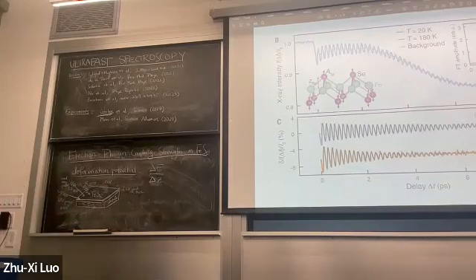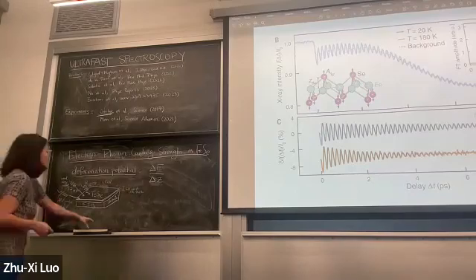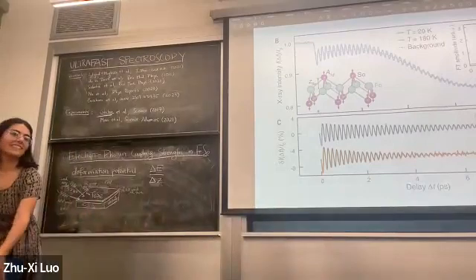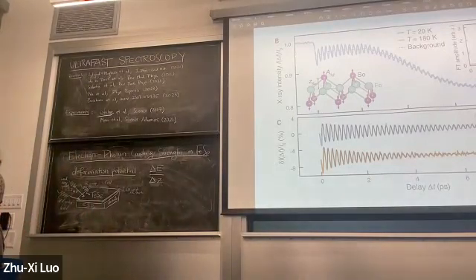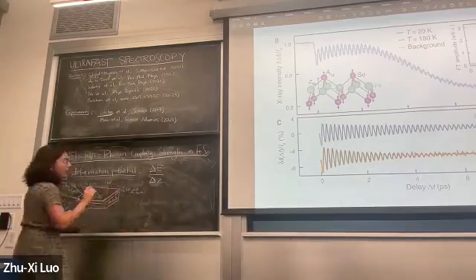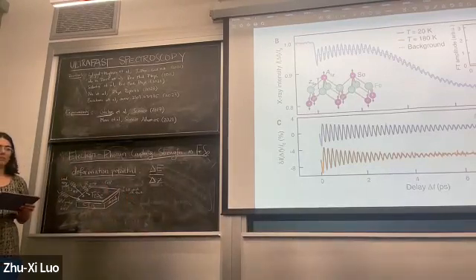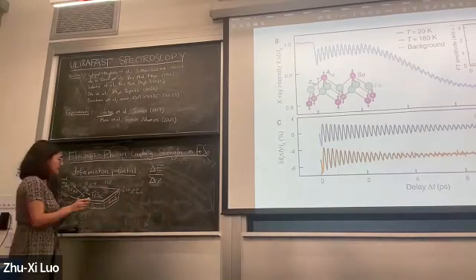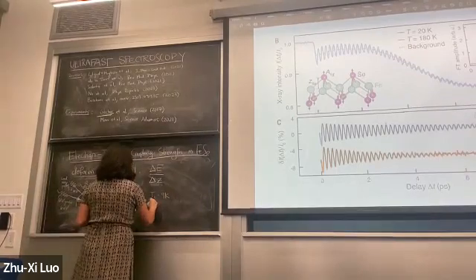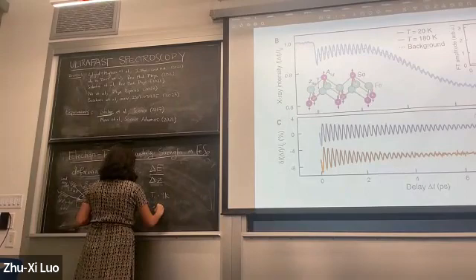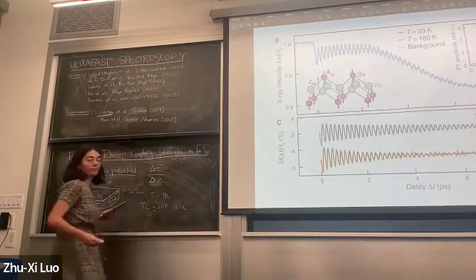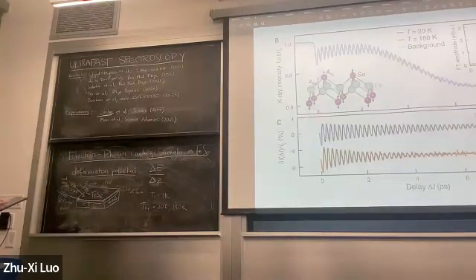Okay, so the procedure is, yeah, a few stupid questions. So you mentioned measuring the band structure at this point in the superconductor. Oh no, yeah. At this point, we're above the critical temperature. I should mention that. We're at ambient pressure, the critical temperature is around 9 Kelvin for this material. But the experimental temperatures will be 20 Kelvin and actually 180 Kelvin. Oh, this is just the temperature that we're running the experiment at.